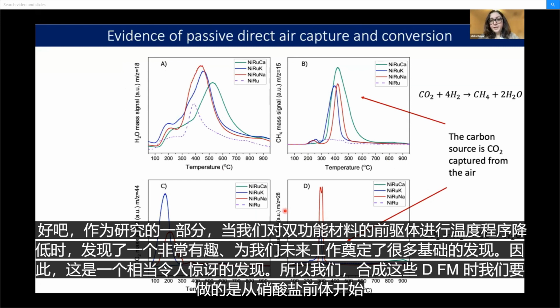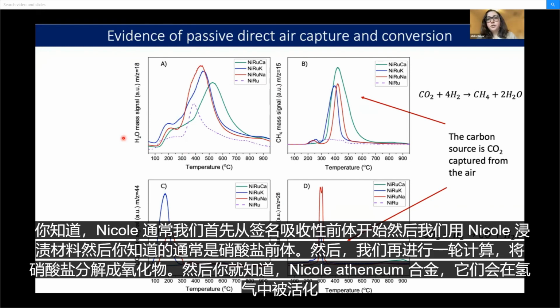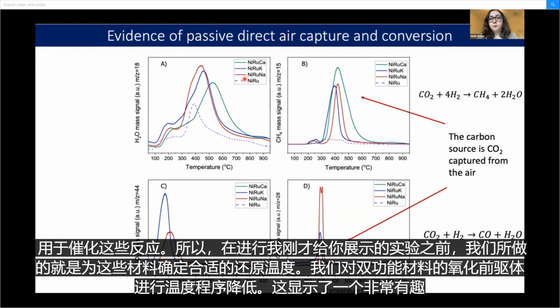Okay, so one finding as part of this study that was really intriguing, and that was forming a lot of the basis for our future work, happened when we performed temperature programmed reduction on the precursors to the dual function materials. So this was a rather surprising finding. What we do when we synthesize these DFMs is we start with nitrate precursors of nickel and ruthenium. We first start by calcining the adsorbent precursors, and then we impregnate the material with nickel and ruthenium nitrate precursors. And then after that, we do another round of calcination to decompose the nitrates to produce oxides. And then the nickel ruthenium alloys become activated in hydrogen for catalyzing these reactions.